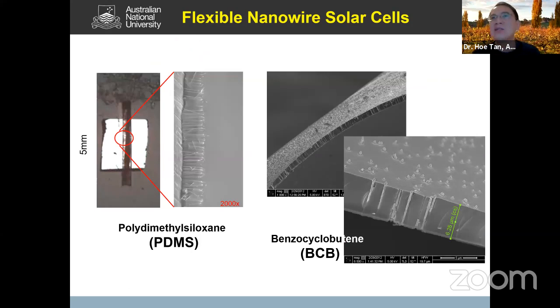During the optimization of the fabrication process, as I mentioned before, we planarize it with some polymer such as BCB. We found that, you know, once it is planarized, we can actually peel off the whole BCB layer with the nanowire intact in the BCB layer. Okay, and similarly, we can do the same with PDMS. Okay, and what this shows us is that it gives us now an opportunity to make flexible nanowire solar cells. Okay. So for example, if you can make top contact and then you can make bottom contact, then potentially you can have what you call a flexible nanowire solar cell.